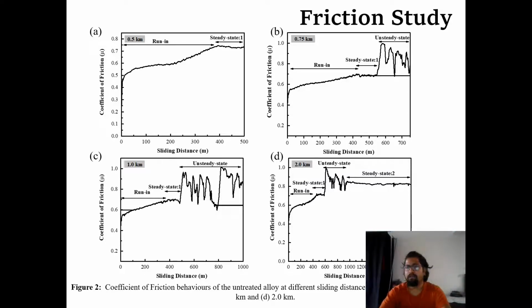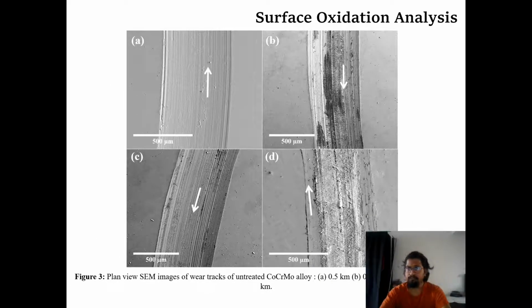And then further at 1 kilometer and 2 kilometer, this behavior changes drastically, and we can see that at 1 kilometer we had a very big unsteady state region, which shows that there is a formation of various oxide islands and all. And at 2 kilometer, after around 1100 meter, it starts stabilizing again and shows a very steady state region, and this defines that at some point the oxides start stabilizing and press into the layer, which we can visualize through the SEM imaging.